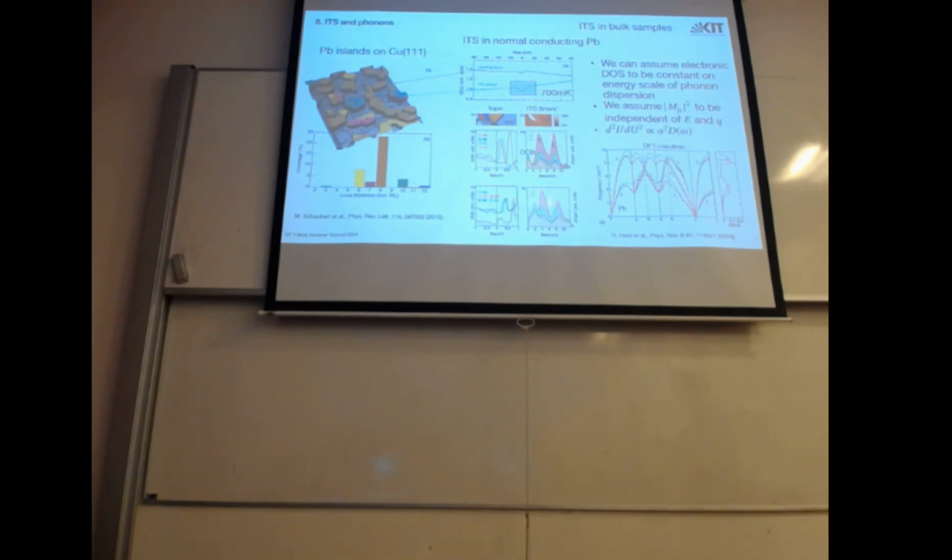Now, the peaks near 0 we know already, they come from the dynamical Coulomb blockade. At very low temperatures and very low electron energies, the state tunneled into is occupied for a long time, so you cannot add another electron. But away from that, we see 2 peaks, and these 2 peaks appear in all of the different islands with different intensity. The peaks are at 4 and roughly 8 milli-electron volts.